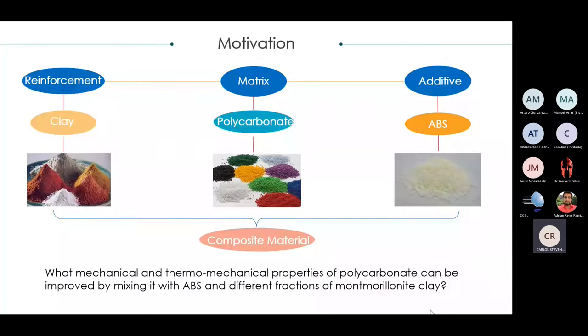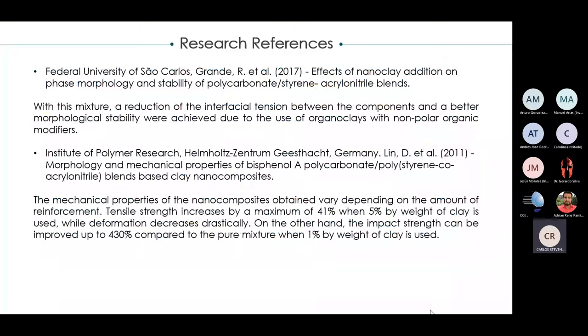Here is the research reference, a quite important part of this research. At the Federal University of São Carlos, Rafael Grande et al. in 2017 studied the effects of nanoclay addition on phase morphology and the stability of polycarbonate styrene acrylonitrile blends. They found that with this mixture, a reduction of the interfacial tension between the components and a better morphological stability were achieved due to the use of organoclays with non-polar organic modifiers.